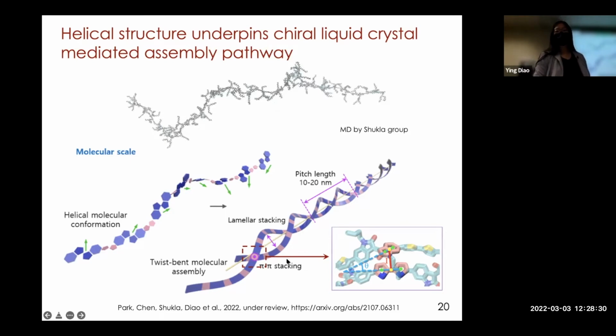Another essential aspect is that these wavy polymers can stack in a staggered fashion to aggregate into helical fibers. That's shown by DFT calculations, that the pi-pi stacking happens in a staggered fashion. The indigo ring and the thiophene ring stack at 45-degree angles, which is a global minimum. That's very different from how we traditionally think about stacking between these polymers. Usually we think they're cofacial, but actually they're staggered. And that enabled such helical assembly to happen.